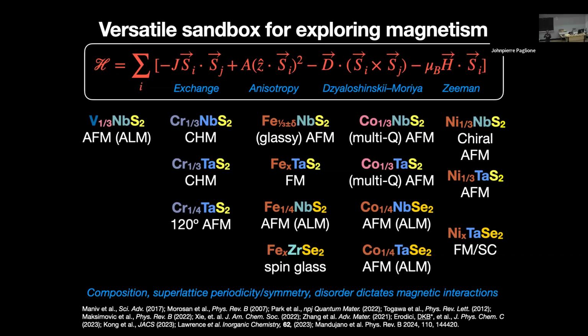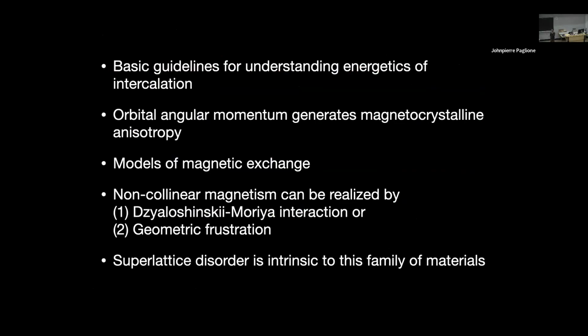What's really interesting about these materials is the playground they afford for looking at the various effects that can be tuned to give rise to different kinds of magnetic order. We can think of the magnetic exchange and its interplay with anisotropy and the Dzyaloshinskii-Moriya interactions, which, as I'll talk about more, give rise to canting of spins. They can promote orthogonal alignments of spins versus parallel and antiparallel. As you tune the periodicity or symmetry, or as I'll talk about, disorder, you're able to play around with all these different terms, how they interact with each other, which one dominates, and so on. That gives you a really large playground. So we're going to walk through a few cases and look at a subset of these interactions, try to understand them to some level, and then see if that gives us any guidelines, any basic principles, for designing materials within this space.